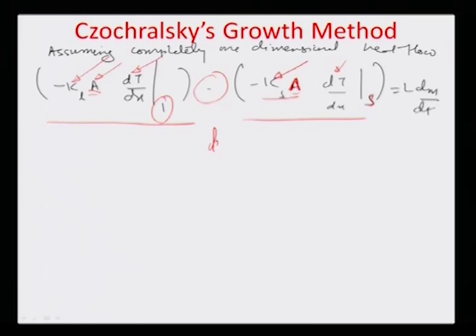So, if you assume that the rate at which the solid material gets formed is dm by dt, as you can see in this particular illustration here, and L being the latent heat of formation, which is in terms of how much heat per kg is lost in order to form the solid. So, L dm by dt is really nothing but the rate of heat loss in terms of formation of the solid bonds. Rate of heat loss can be equated in terms of heat going per unit time into the zone of fusion minus heat going away from the zone of fusion per unit time.